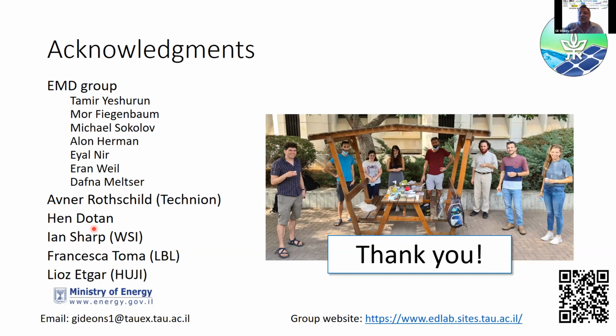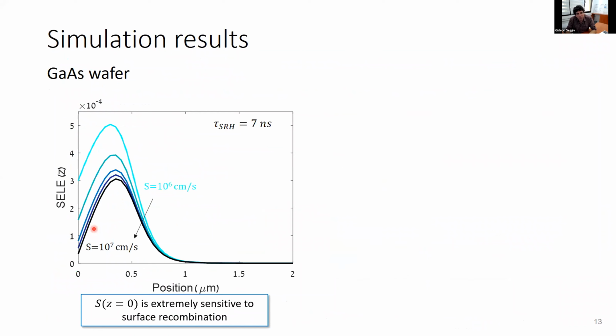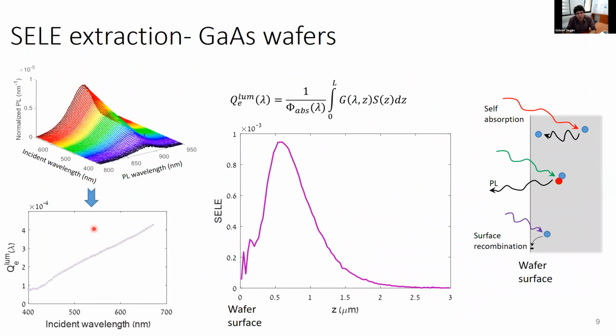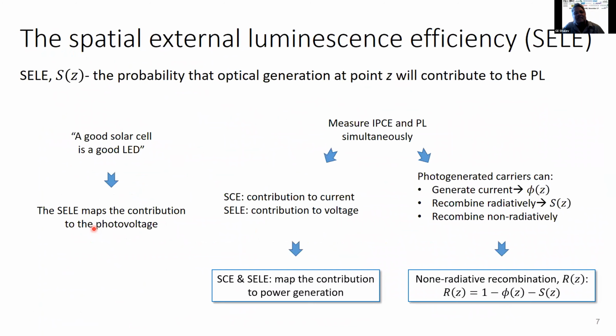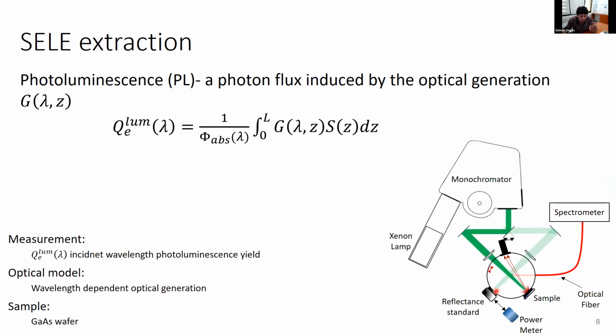So I'll just ask a short technical question. When you do the external luminescence, you manage, both in simulation, in calculations, and in experiment, to collect all the photons from half a solid angle. Okay, so in terms of experiment, we work with an integrating sphere, and right now the cell, the material, the wafer, is pretty flush with the surface of the sphere. It's not inside. It's not at the center. It's at the surface, and the way to calibrate is with respect to a fully diffusive reflection standard.